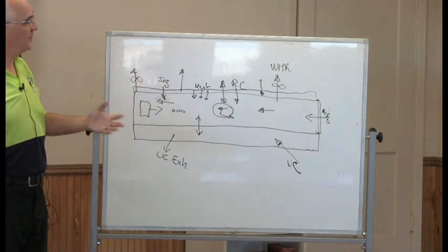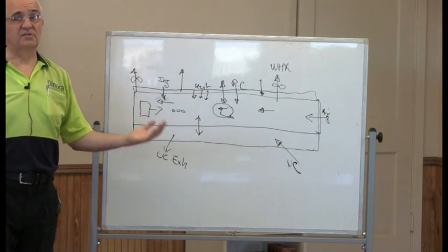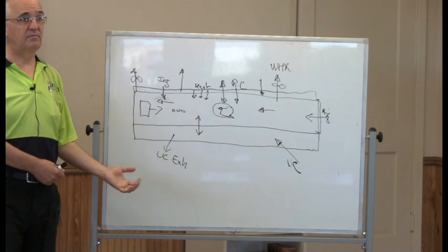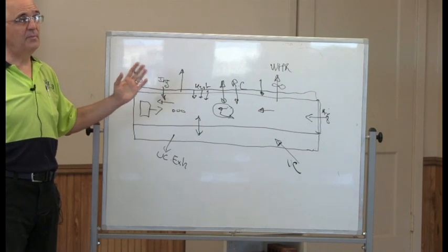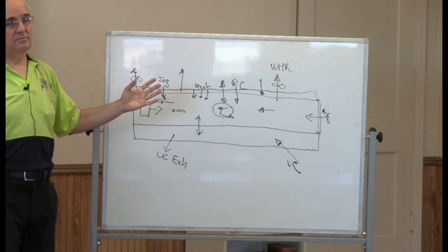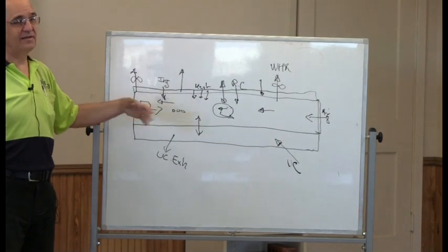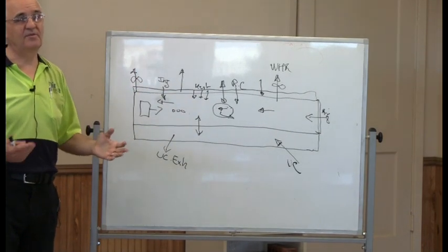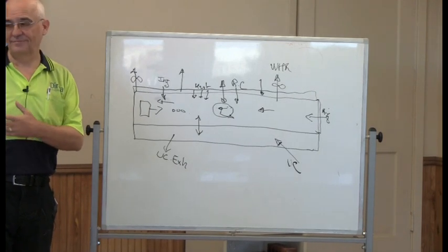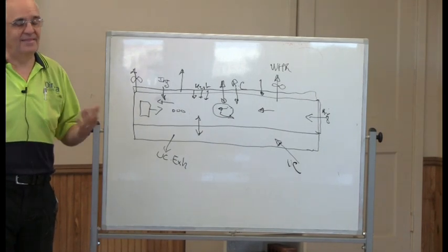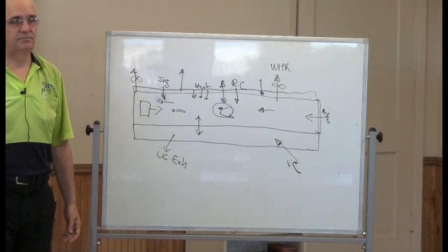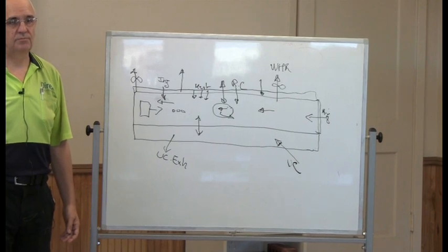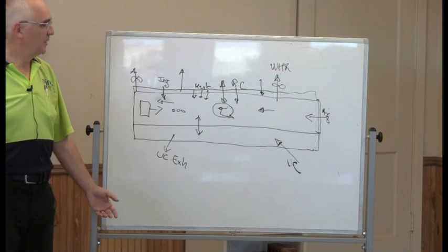And it's easy to forget because we see the kiln as a big source of energy. So let's pull it. It doesn't matter because, oh yeah, my burners keep up. Yeah, but now we make the burners run not just for the kiln and not just for the process, but as an additional burner for the dryer. And that doesn't work. We had hotspot issues, and I would not be at all surprised if a lot of it came from the fact that we were maybe stalling the air movement and causing that.